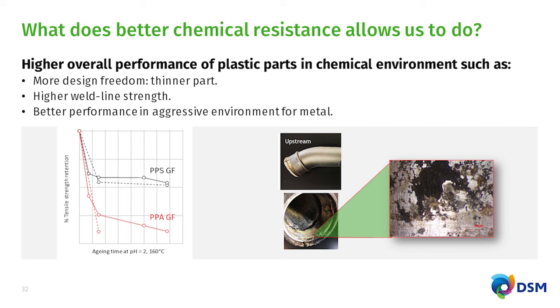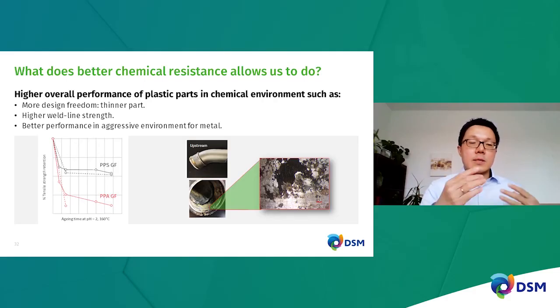So I hope you are convinced now that if we have higher overall performance plastic, so we choose the proper plastic for our certain applications within a certain environment for automotive, we will be able to then have more design freedom, meaning, for example, we can go to a thinner part because we are now certain that the reaction rate is very low, the diffusion coefficient is really low, as well as the solubility limit of the chemical into the polymer is also low. So if all those parameters are low, we basically have a very good resistance of polymer.